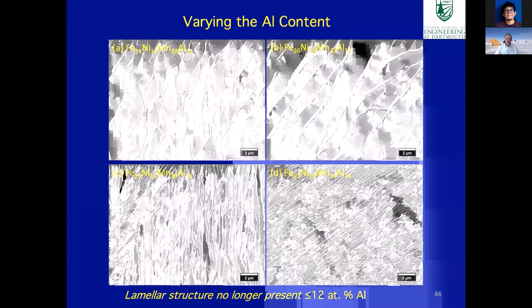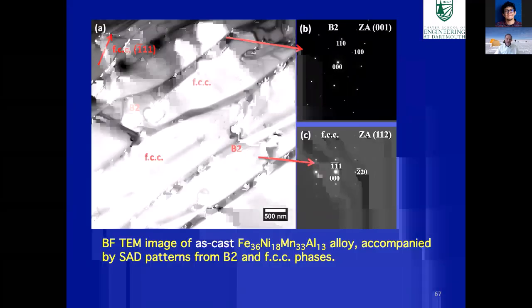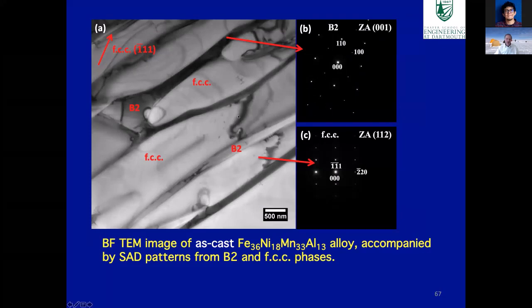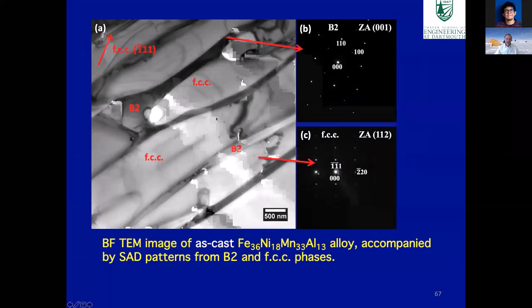So one of the things we did was vary the aluminum content of the alloy. So these are lower aluminum contents than before. And as you decrease the aluminum content, the lamellar spacing changes. So this is with 13 aluminum. Now we've got much more of the FCC phase, and the B2 phase is much thinner lamellae.